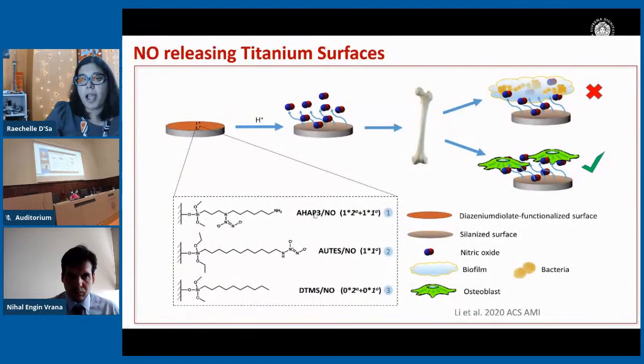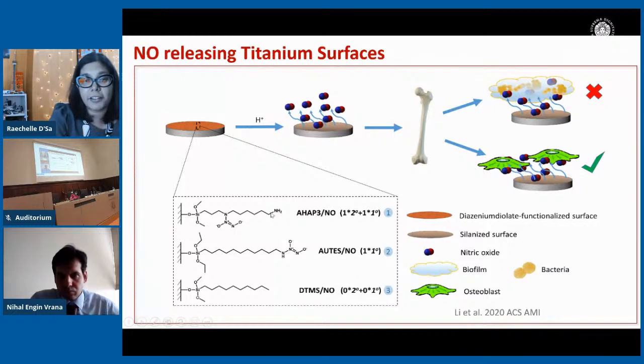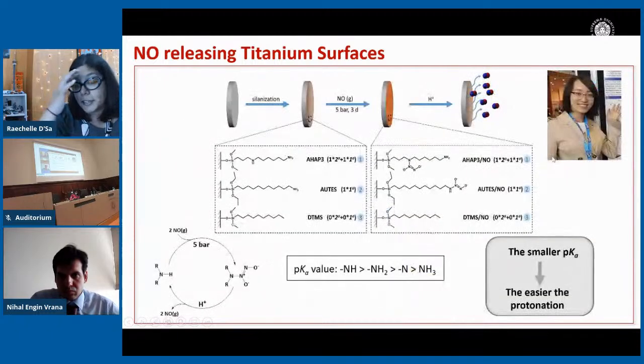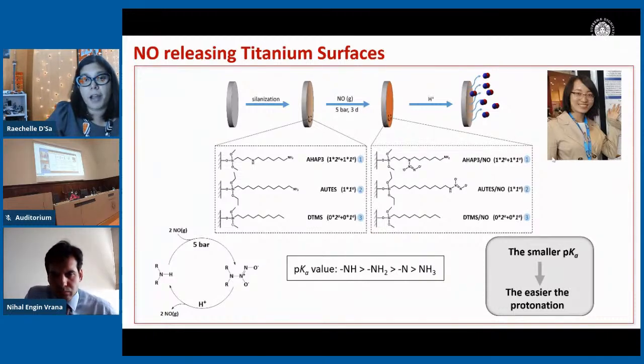So the work that I'm going to be describing for you today is based on titanium surfaces that we functionalized with different silane linkers and tethered nitric oxide onto these silane linkers so that we can discourage a bacterial response and encourage an osteoblast response. So the silane linkers we picked for this study were based on some work that had been previously done by a colleague within our department, Jude Kern. She had looked at different silanes onto glass surfaces and seen how amino-terminated silanes can encourage an osteoblast response. And what she found was that this 11-chain silane with an amino-terminated group has a positive osteoblast response.